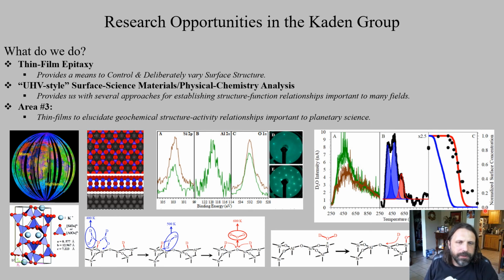I won't go into the details too much here, but basically through this type of an analysis, we were able to pretty well lock down pathways by which this occurs. So here's this recombinative desorption in red and the temperature. And furthermore, we could get out the energetics of this, which were such that for the duration of time that the moon is hot and the temperature that the moon reaches in daytime, this is happening pretty much all the time in these equatorial regions. And then, of course, as you get colder towards the poles, it drops off a bit.